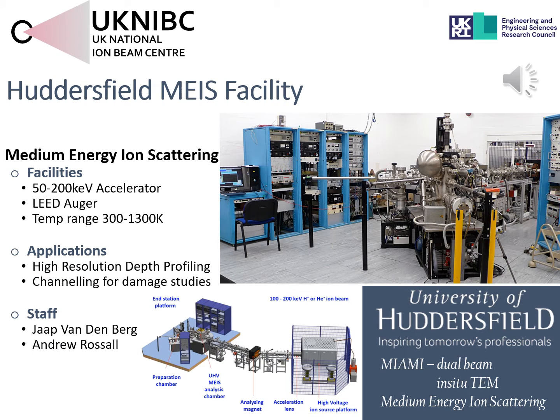Also at Huddersfield is the MEIS facility, the Medium Energy Ion Scattering facility, which is a 50 to 200 kV ion accelerator, which is used for scattering ions from surfaces, usually light ions. And there we're looking for the backscattered particles. We're looking at the high resolution depth profiles of the elements that make up the surface region of the material. The sample can be aligned into particular crystallographic directions so that you can channel the ions in perfect crystals, and therefore you can look at defects that are created by other means, either irradiation, implantation, or other surface treatments. So you can look at the damage that's introduced in the surface region as well using the channeling technique.